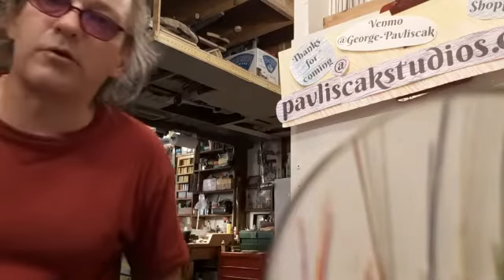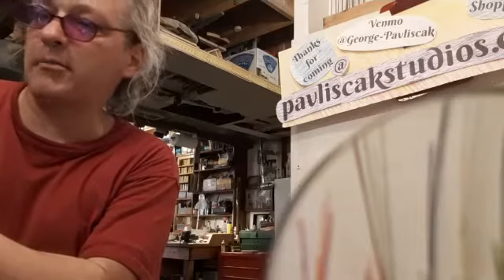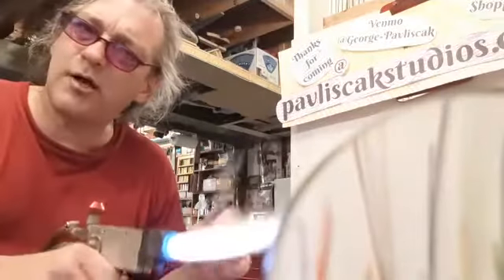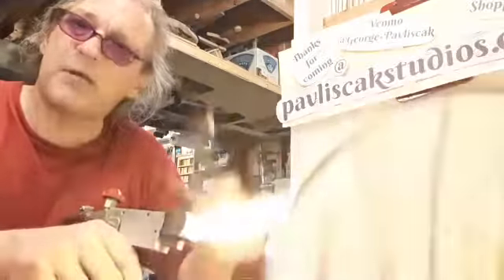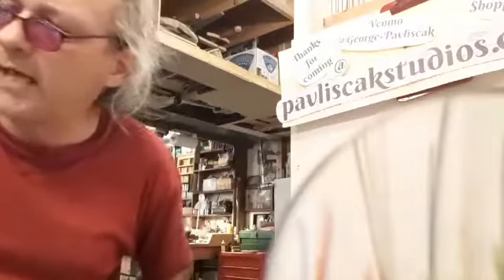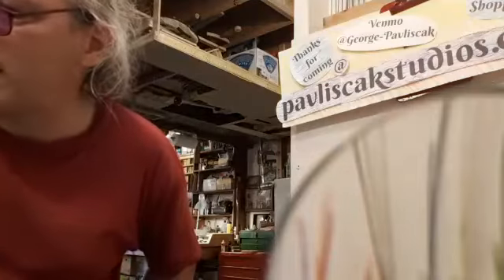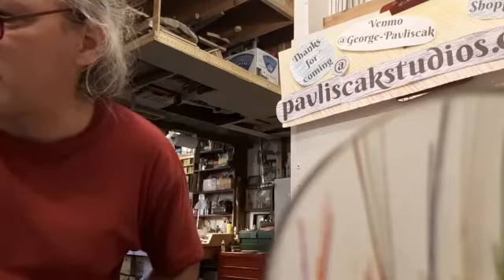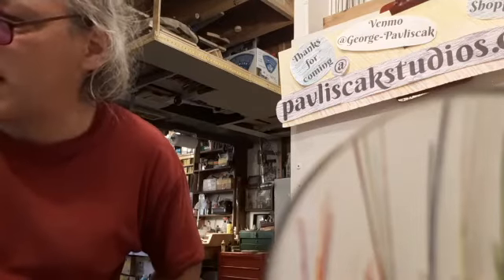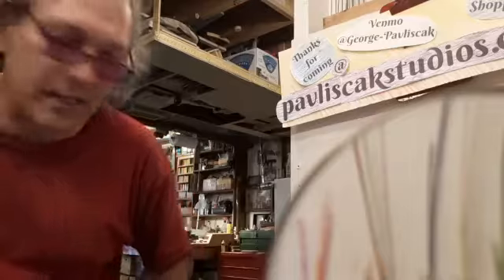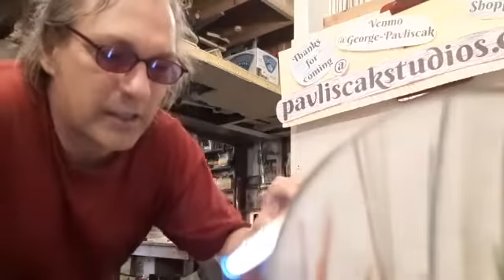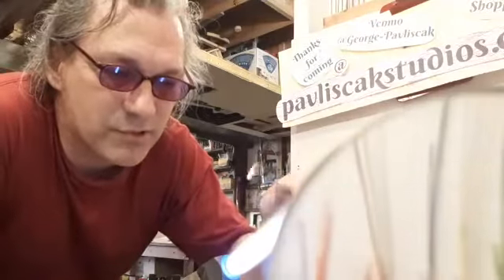Generally, when you're doing this, I turn down the propane a little bit. Sometimes to get particles off the torch, because I'm picking it up and disrupting it, I'll tap it a few times if it gets any loose carbon off first. Then I'll polish it usually in 3 passes, getting that nub attachment point hot enough so I can see any irregularities. Let it cool, heat it back up, let it cool, heat it back up. And by that point, it's fallen into a perfect surface.